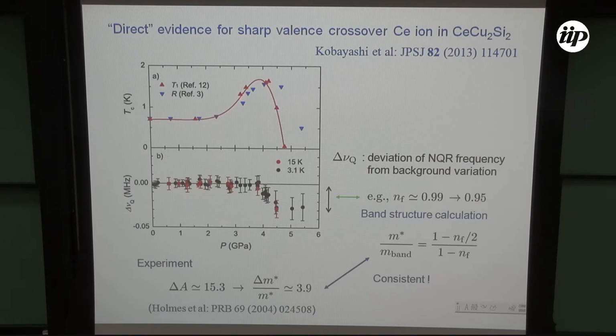Actually, it was recently reported by NQR measurement under pressure. At this pressure, where Tc has a maximum, the NQR frequency decreases from the background linear variation. According to the band structure calculations done by Harima, this change corresponds to, say, 0.99 to 0.95. So delta A corresponds to the decrease of m star by 3.9. This corresponds to this kind of variation. So in that sense, this is totally consistent.